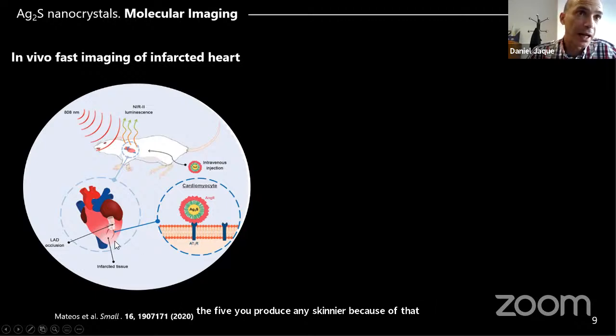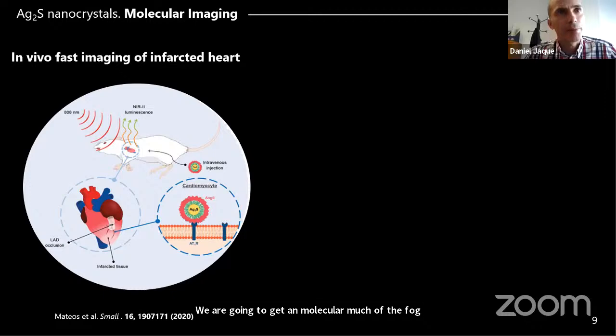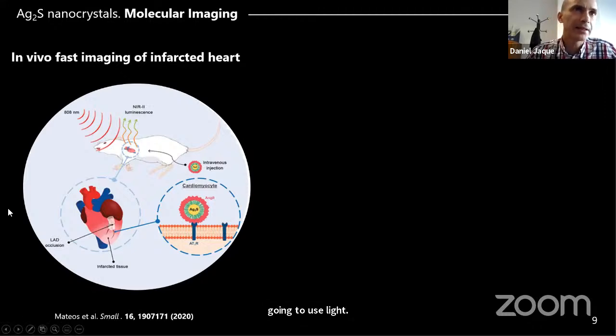And because of that, the cells of the myocardium express this gene, okay, the AT1R. So you have silver sulfide nanoparticles that are decorated at the surface with the antigen, okay, and then these nanoparticles are going to be injected in the tail and will accumulate in the tissue that has been damaged due to the infarct. So we are going to get a molecular image of the infarct by using functionalized nanoparticles. And for that, you are going to use light and not ionizing radiation. So the idea is clear.